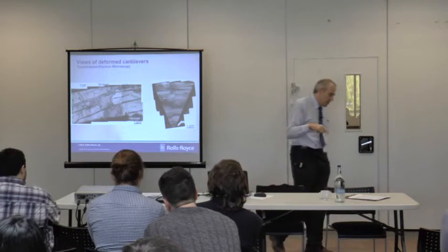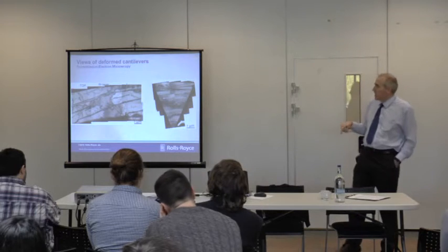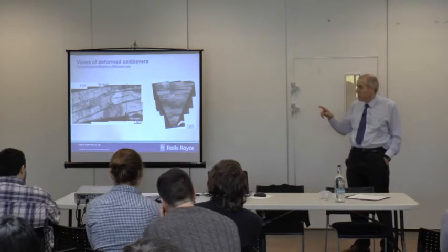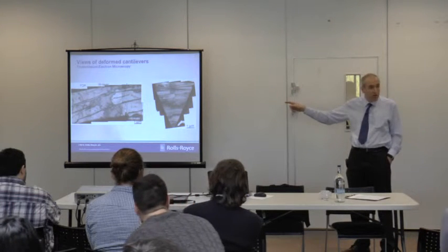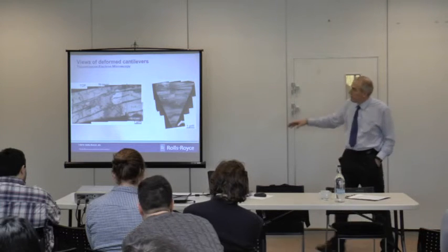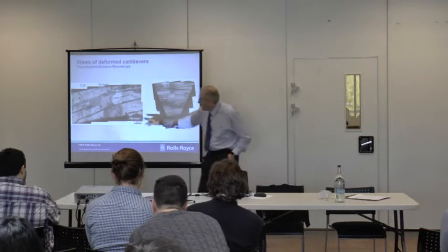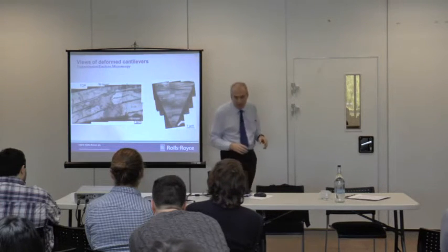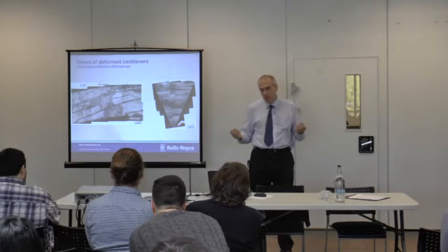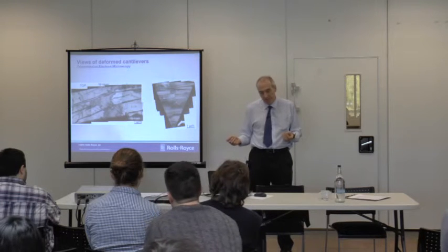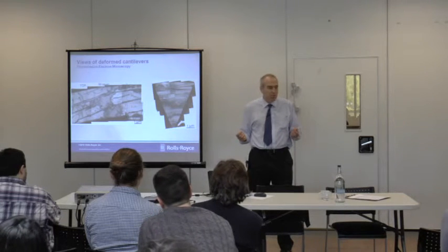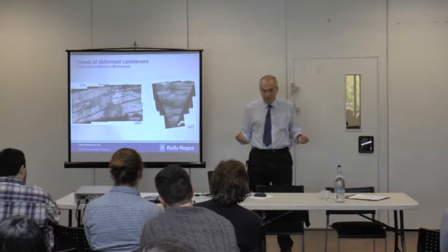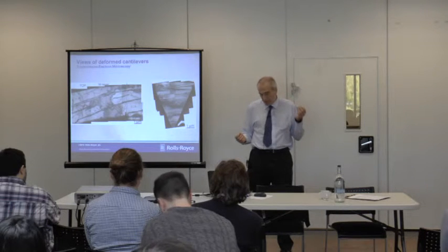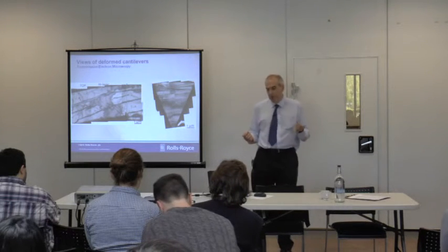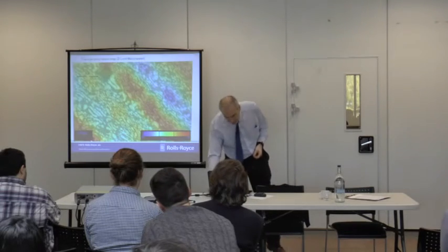We can also go to discrete dislocation modelling and actually model that whole sample and look at where the slip bands, because the dislocations all talk to one another, and you get these planar features in here. You can actually have a pretty good go at modelling that. So there's a convergence where it's small enough test piece sizes that it's tractable, certainly at molecular dynamics, at discrete dislocation level, to get real numbers out.